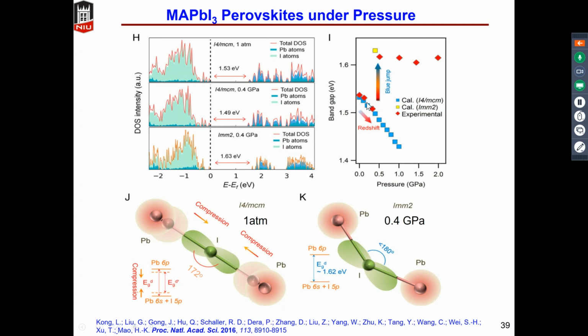Now, our theoretical calculation indicates that if there's no phase change, then the band gap of this MAPbI3 single crystal would continue to decrease. So it indicates that if we can keep the phase without phase transition, then the band gap can continue to decrease. And the reason why this MAPbI3 encounters this phase change is because the lead and the iodide bond is not perfectly linear. It's about 172 degrees. So there's a kink in this bond. And so when the pressure increases, this bond folds, causing the phase change.